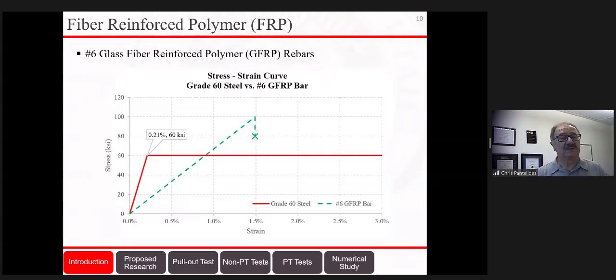So what are the properties of these materials? We use number 6 glass fiber reinforced bar, as you can see here in green, which has pretty good tensile capacity. It has 100 KSI ultimate strength and a 1.5% ultimate strain. And as you can see from this graph, it is an elastic material. It doesn't yield. On the other hand, grade 60 steel was used, which has a yield strain of about 0.2% and a yield stress a little more than 60 KSI. This is an idealized graph, but it shows that there are, of course, advantages to using steel. It yields early, and its ultimate strain capacity is more than 3%.